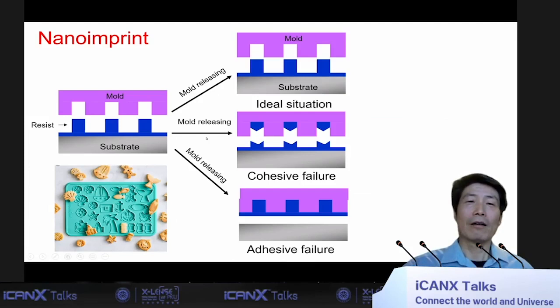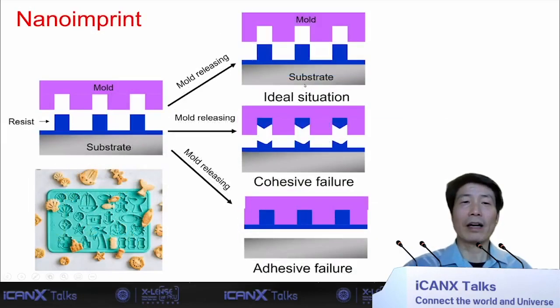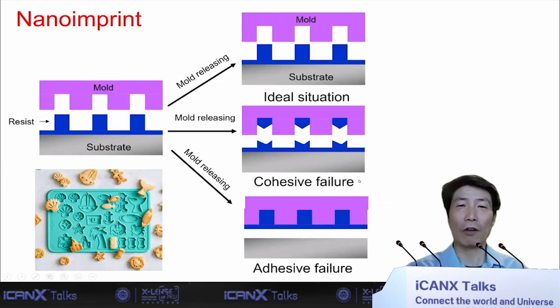But the challenge comes from the separation. This top figure is what you want to get. But if the material is not strong enough, it can break and create defects. Or the adhesion is too strong to the mold, because you can imagine the surface area is huge, but not enough adhesion to the substrate, and you can entirely take off the whole film. That's also a failure. But fortunately, over the past couple of decades, through the effort of many researchers throughout the world, most of these problems have been solved. And this technology has moved on to industrial scale.